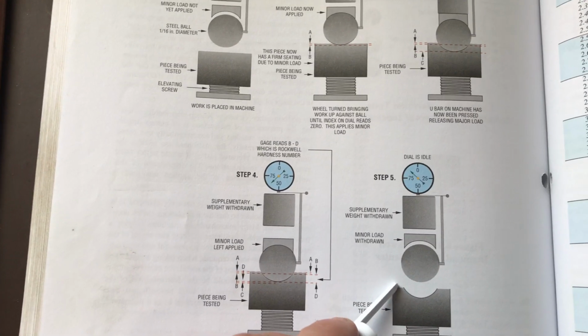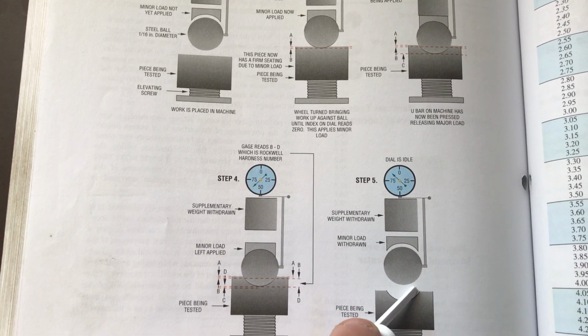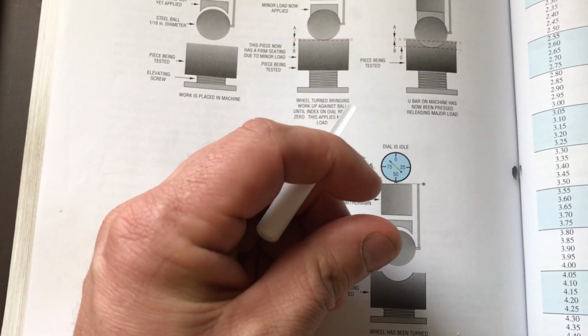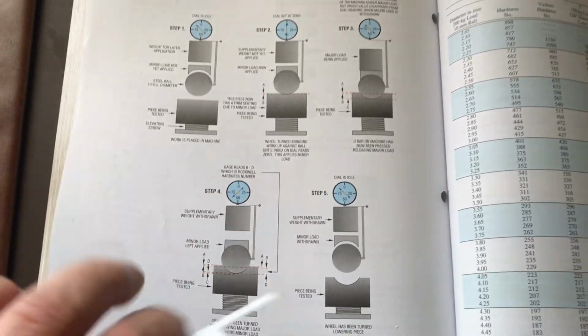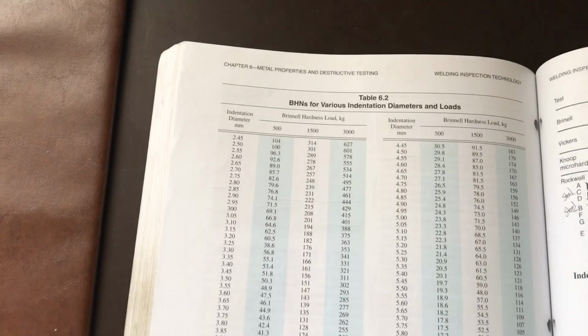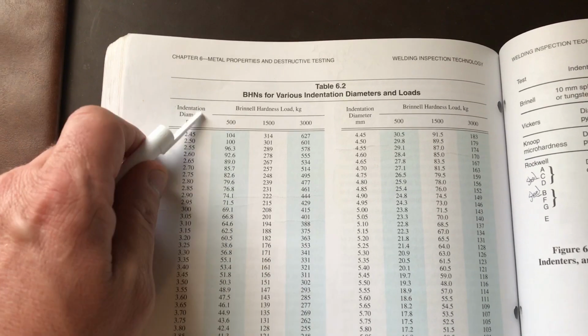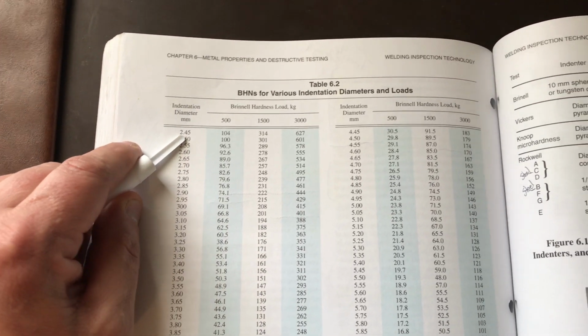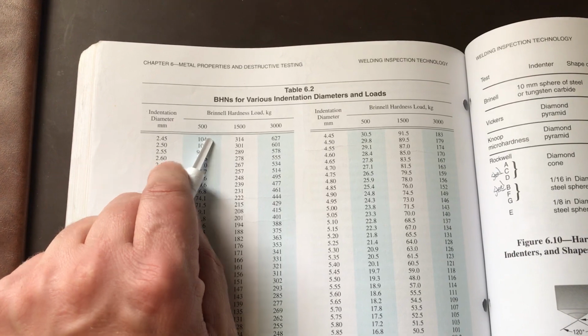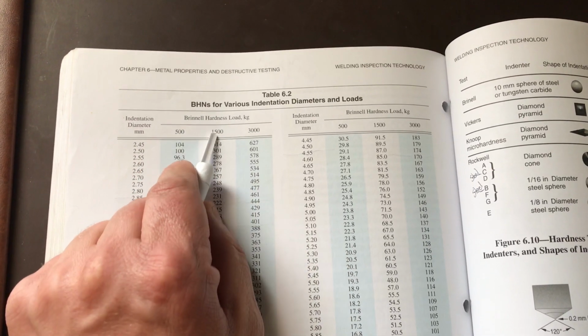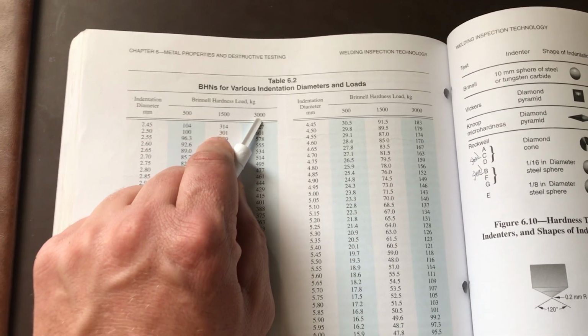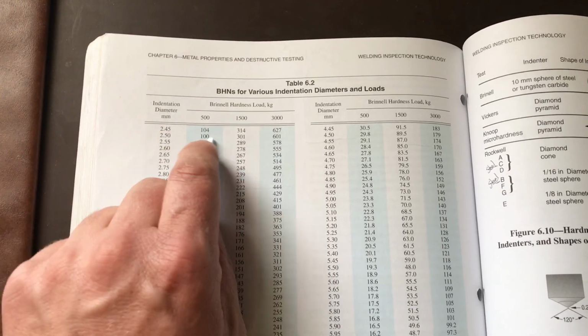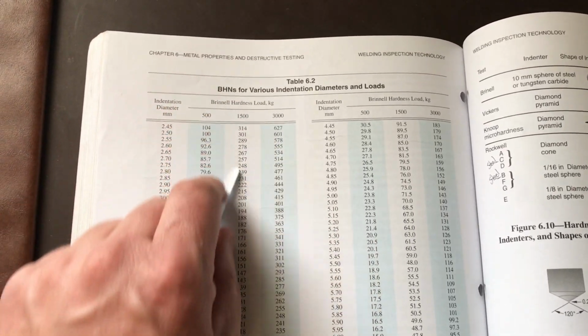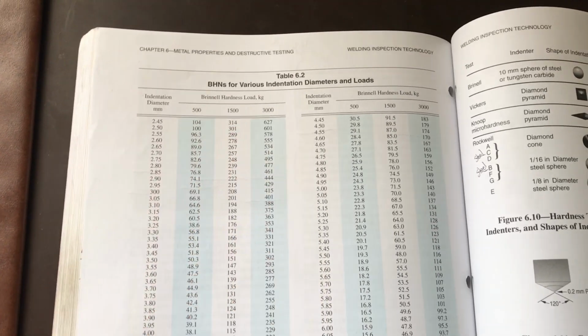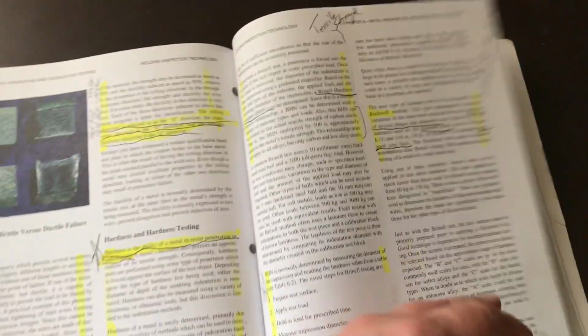We're going to measure the difference from that edge right there to that edge right there, and it's going to be a round surface, or in some cases maybe a diamond. But that's the number we get, and then we come over here and look at the indentation diameter. So it ended up being 2.45 millimeters, and that's going to correspond to, well, what was the load? Was it 500 kilograms, 1,500 kilograms, or 3,000, depending on the material? Then we can see, oh okay, that's what's telling me my Brinell hardness. Nice, okay. Making sense now?